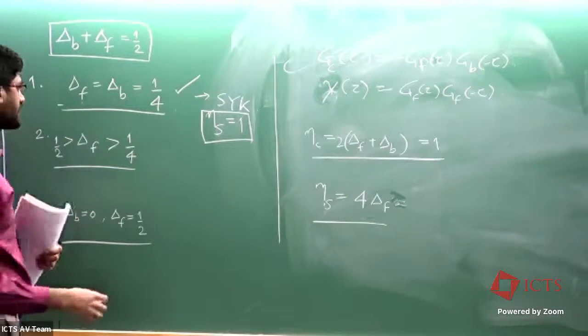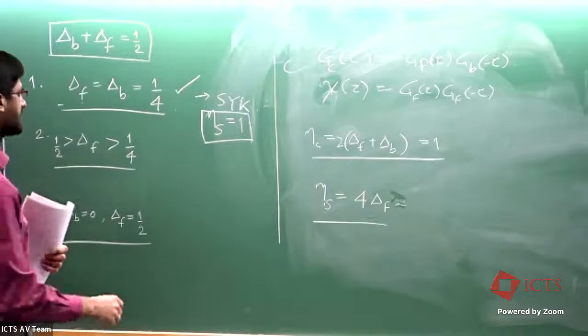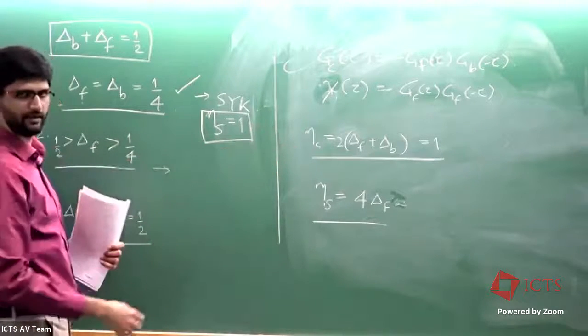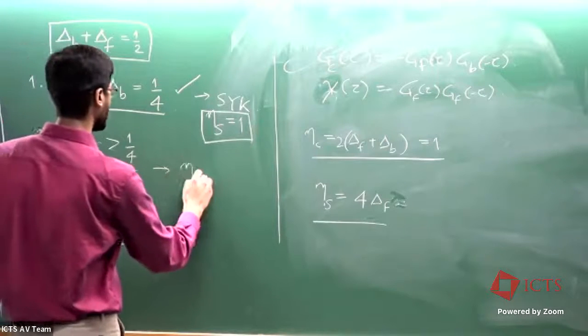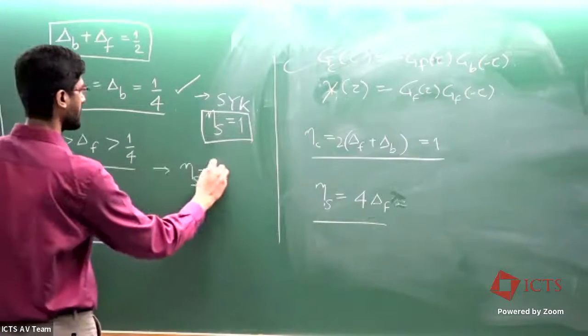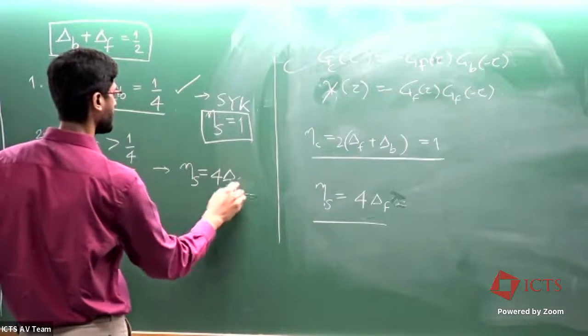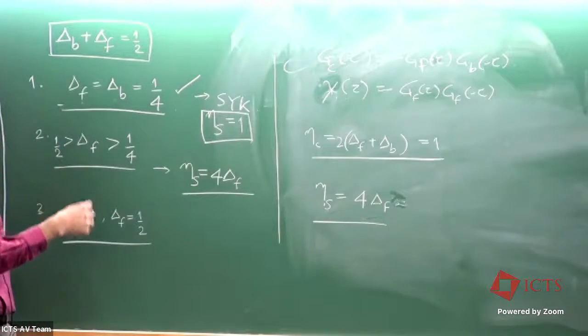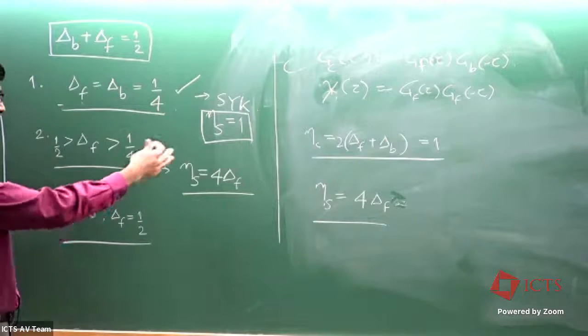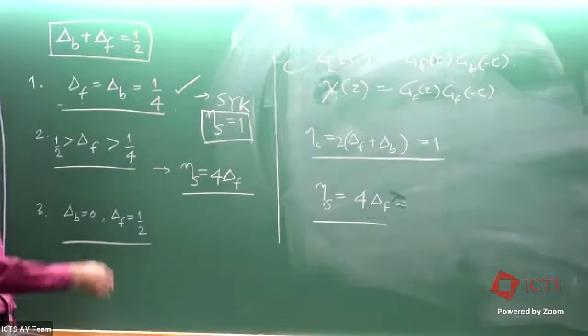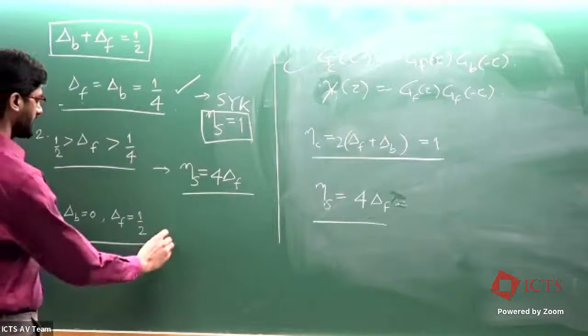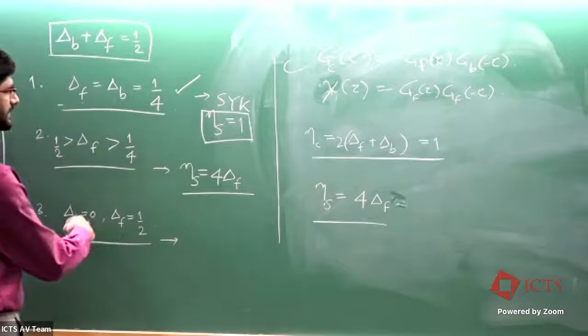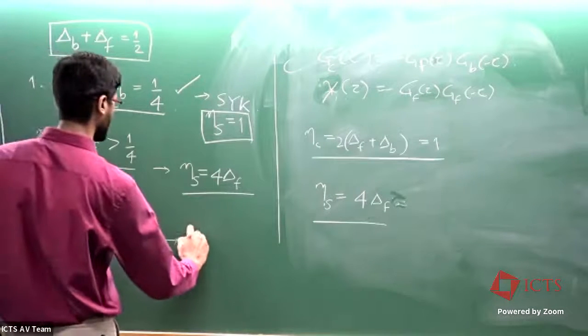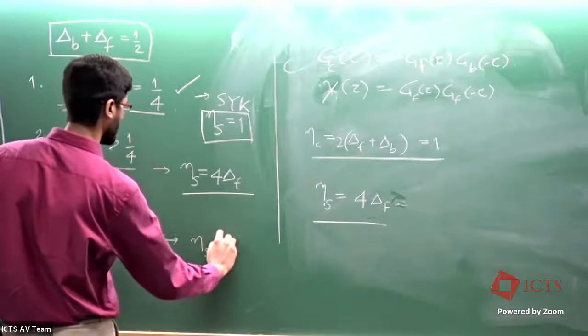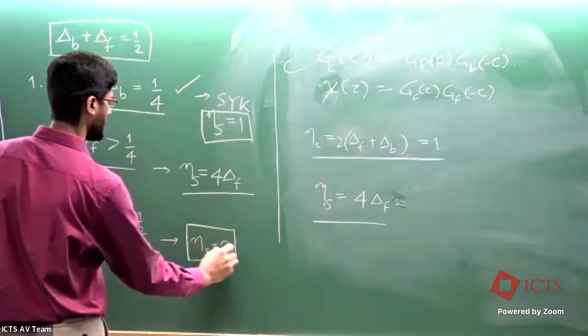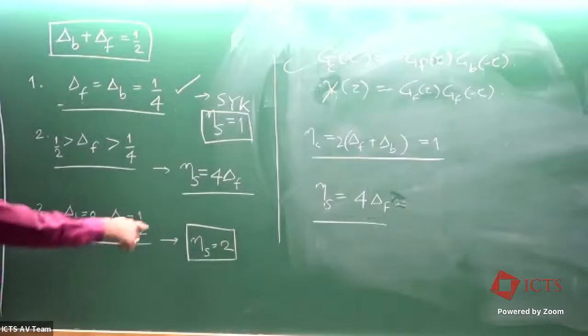So that's the solution. The other solution is also a critical solution. Here again, eta_C is exactly 1. It's Fermi-liquid-like. But eta_S is now, as you can see, not a constant. It depends on delta_F. So it's a continuously varying exponent, depending on what value you choose for the exponent of your fermionic piece, or the bosonic. And the last one is actually slightly more trivial, because this tells you that eta_S is exactly 2. So here again, you have an exact value of eta_S, but this is not a critical solution.